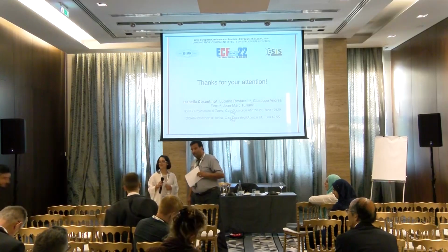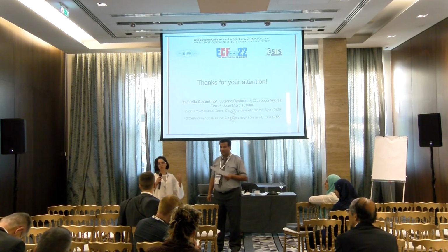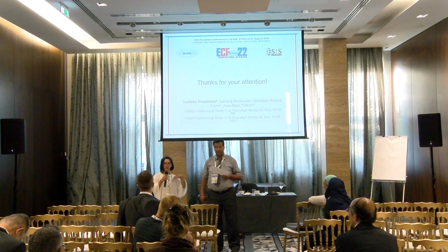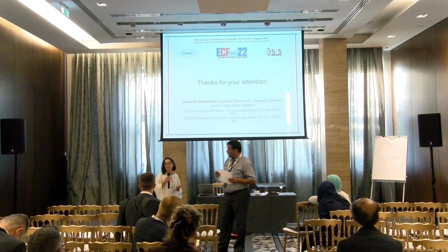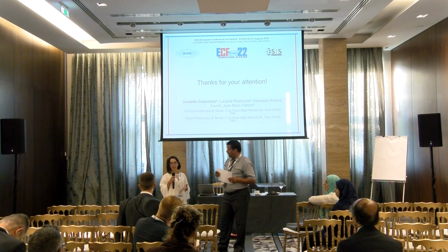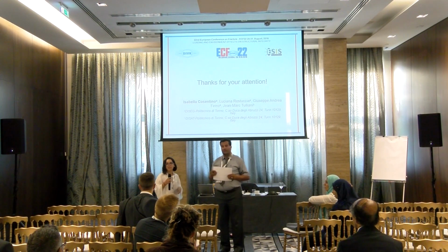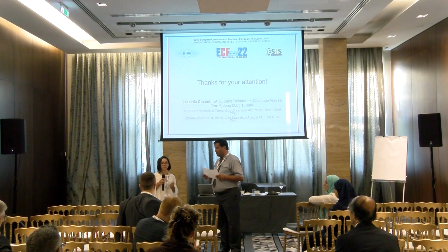Okay. Thank you. For the aluminum alloy 2024, the picture was from other research. Yes, it was found that there was a synergistic effect of both notches and the hydrogen brittle zone because of hydrogen diffusion. But on the 2198, the aluminum-lithium alloy, we haven't found something like this yet. The corrosion behavior is under investigation, to search whether there is this hydrogen brittle zone. And maybe this is some kind of a recommendation.